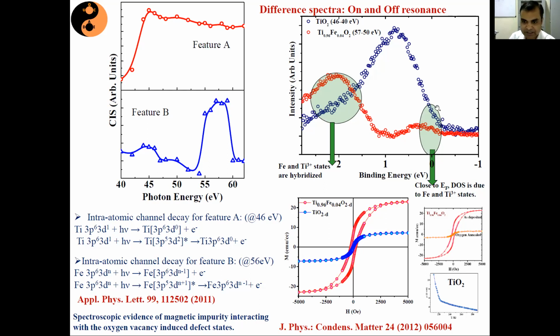Okay, and yesterday we discussed how we confirmed that we have carrier mediated magnetization, this finite degenerate semiconducting like or metallic like behavior, or finite density of states, because of the free electrons created by the oxygen vacancy. How did we confirm? To confirm that, we killed that oxygen vacancy so that we have no contribution from either titanium 3 plus or free electrons.